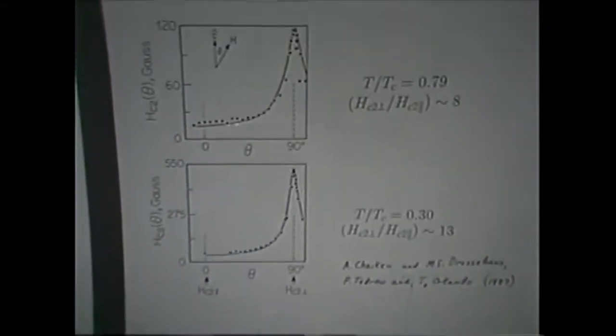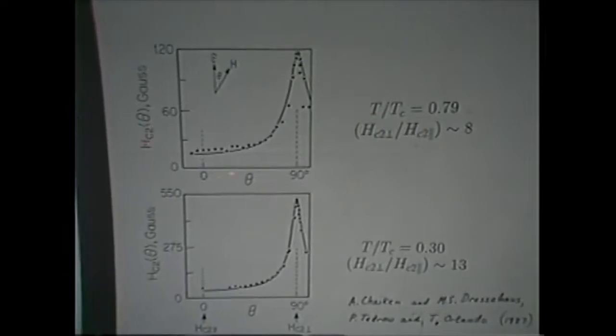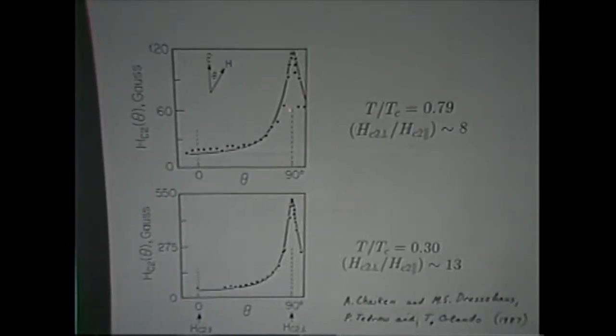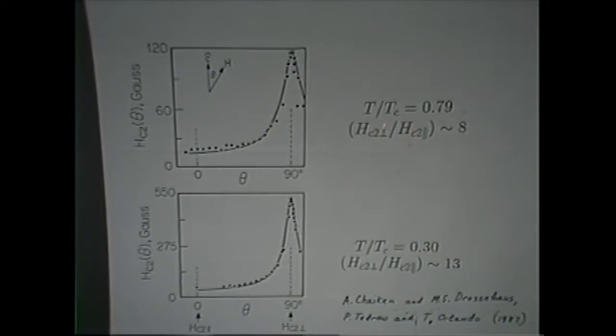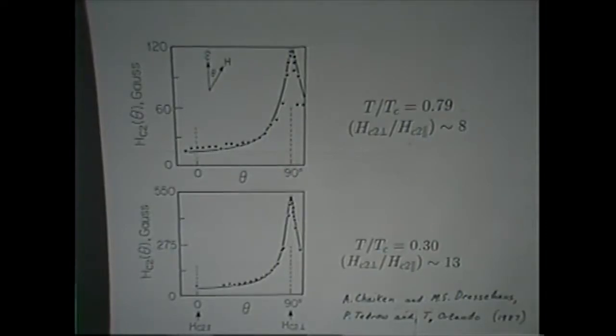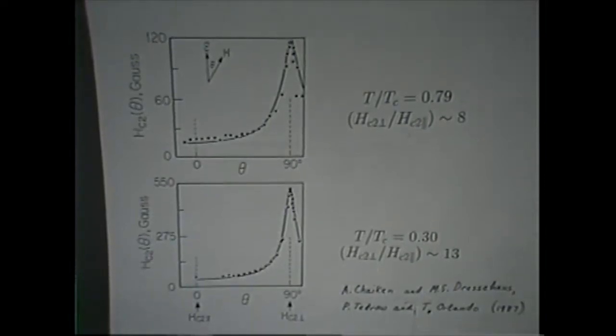And here's some evidence. This is Alison Chaikin's PhD thesis, or the beginnings of it. Here's a plot of HC2 versus angle for a temperature close to the critical temperature, and this ratio here is 8. Then when you get closer to T equals 0, at a reduced temperature of 0.3, this ratio turns out to be significantly larger. Unexpected from a mean field theory model for anisotropic superconductors.